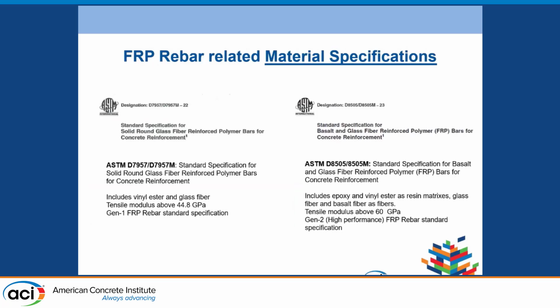Okay, regarding the material specification, for ASTM there are two material specifications. One is D7957. This is considered the generation 1 FRP rebar standard specification. The tensile modulus requirement is 44.8. It includes vinyl ester and glass fiber as the material choice.